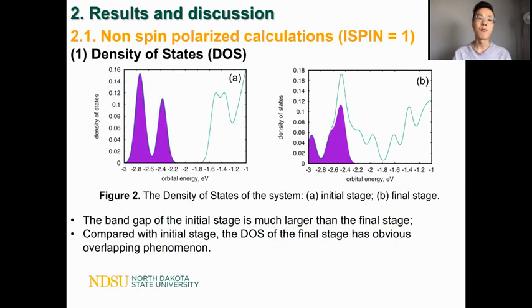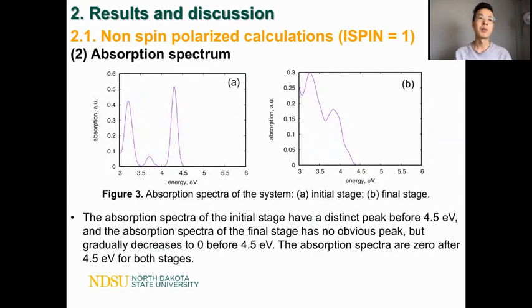Firstly, I studied the density of states of the system when it didn't consider the spin polarized calculation. As you can see from figure two, the band gap of the initial state is much larger than the final state, and compared with the initial state, the density of states of the final state has an obvious overlapping phenomenon. Okay, next, please.